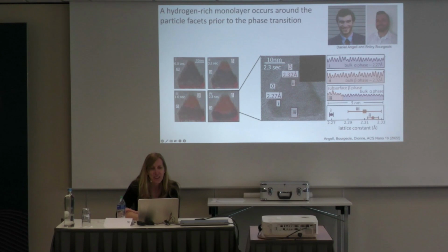And what we found is that hydrogen expands basically the entire subsurface of the nanoparticle. So it's as if once there's a tip that the hydrogen enters into, it diffuses along the first few monolayers, usually just the first 3 to 4 monolayers of that palladium nanoparticle.